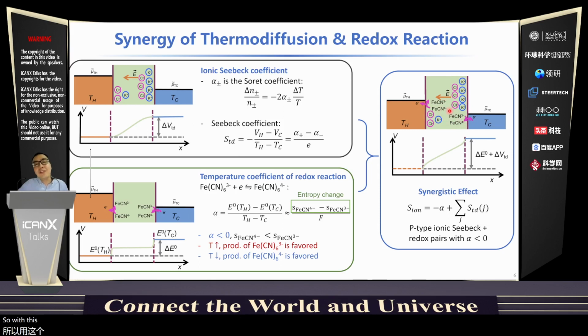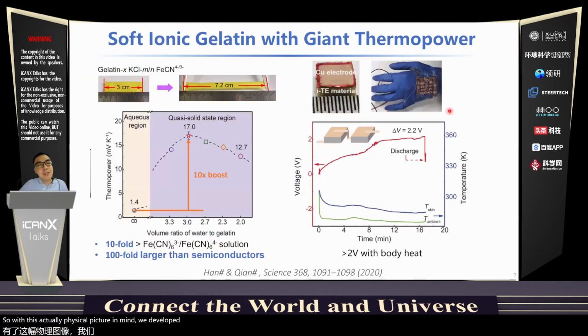With this physical picture in mind, we developed an ionic jello. Basically, we make a jello that contains ion providers, which is KCl, potassium chloride, and ferrocyanide as the redox couple. We make the electrolyte quasi-solid state, so that we are free of encapsulation issues. In this material, we achieve a record high thermal power in quasi-solid state electrolytes, which is 17 millivolts per Kelvin. That is 10 times larger than the aqueous solution of ferrocyanide, and 100-fold larger than most semiconductors.